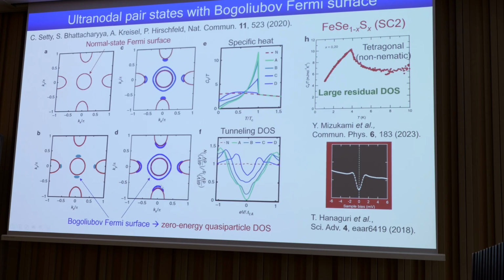Then you can immediately calculate the specific heat and the tunneling density of states, in which you can easily find these zero energy states and zero bias conductance, which looks consistent with what we observed in this FeSe1-xSx region. So this is very attractive for experimentalists. However, there is a big assumption that time reversal symmetry is broken in this material.